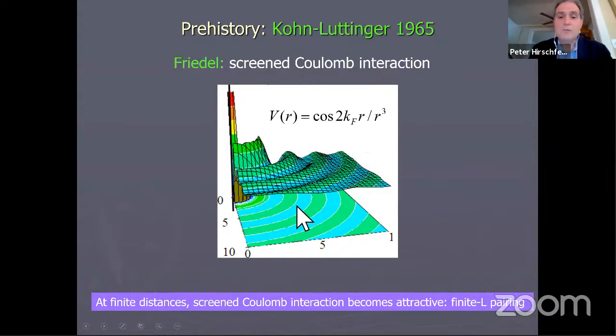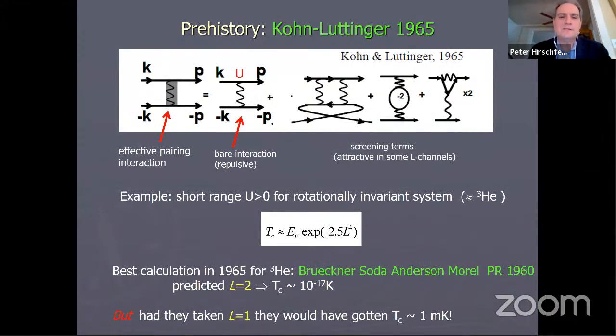And you can imagine that if you create a wave function which lives in the attractive part of this interaction, you can still form a bound pair, even though the overall interaction is repulsive. And that gives you finite angular momentum pairing because of the need to take advantage of those negative regions. So Kohn and Luttinger calculated the effective pairing interaction by looking at all possible processes between a pair of electrons with K and minus K scattering into a pair of electrons with P and minus P momenta, and with this repulsive interaction U exchanged, and they summed diagrams up to second order and evaluated the critical temperature.